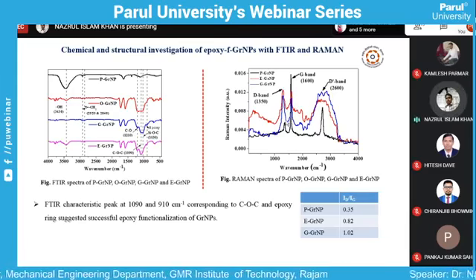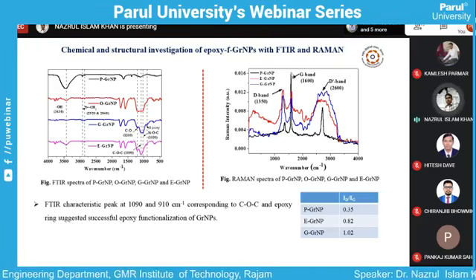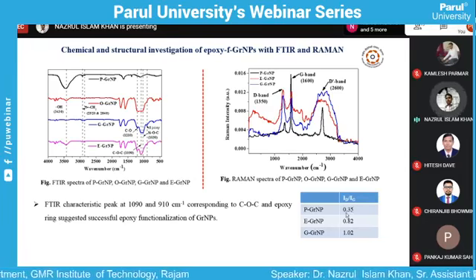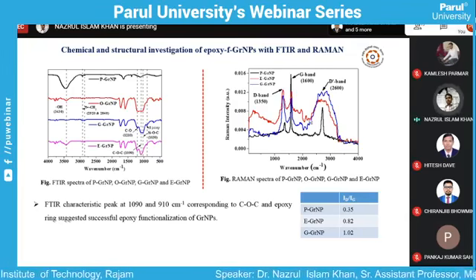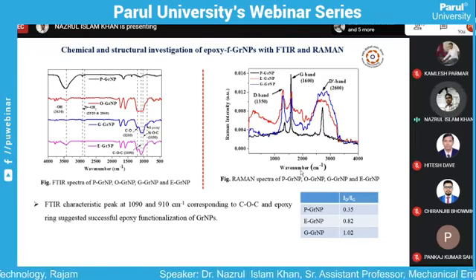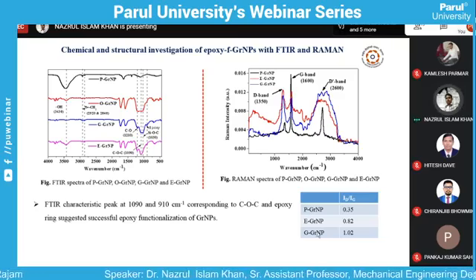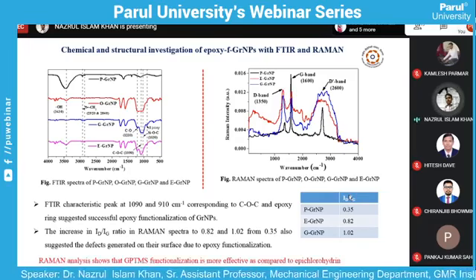Another indication is that in pure graphitic nanoparticle, the ratio of defect band to graphene band is very less, meaning defect is very low. But when we add those foreign materials on the surface, defect intensity becomes high, and due to that, the ID by IG ratio increases with respect to different functionalization methods. This is also an indication that successful functionalization has taken place.